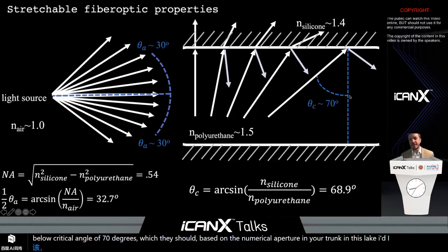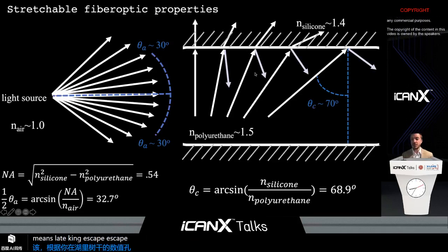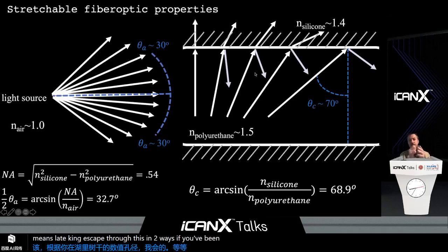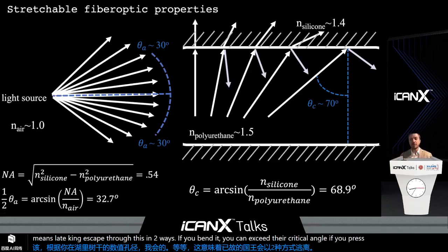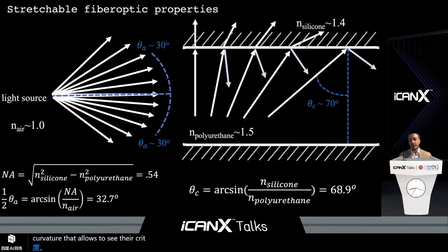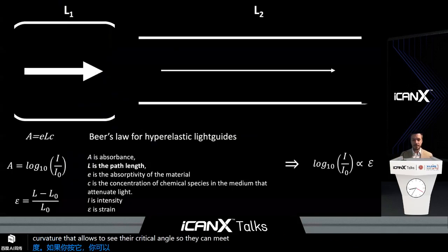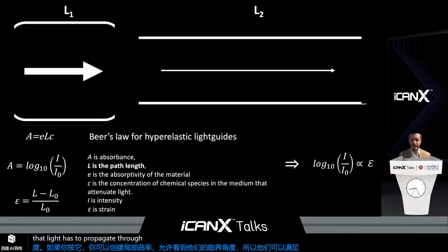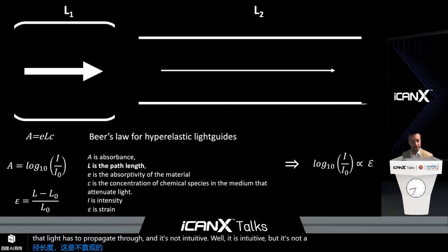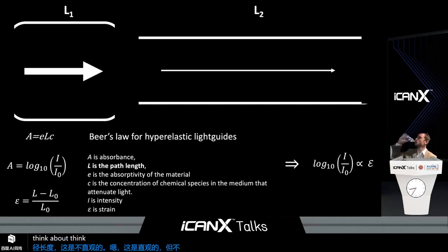Light can escape from this in two ways. If you bend it, you can exceed that critical angle. If you press on it, you can create local curvature that allows it to exceed that critical angle. So light can leave in those two ways. But also, if you stretch it, you're increasing the path length that light has to propagate through. It's not something normal people in fiber optics think about, because they're used to inextensible light guides.